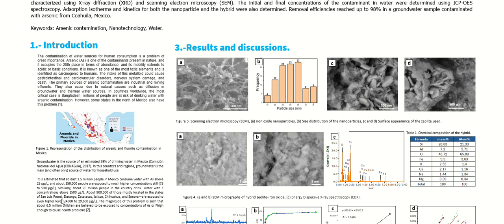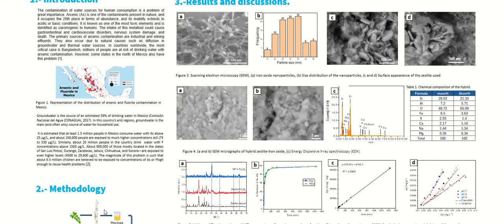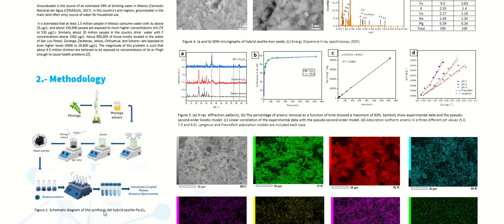About 900,000 of those, mostly located in the states of San Luis Potosí, Durango, Zacatecas, Jalisco, Chihuahua, and Sonora, are exposed to even higher levels, 4,500 to 29,600 micrograms per liter of arsenic. Methodology. To obtain the moringa extract, Soxhlet extraction was used.